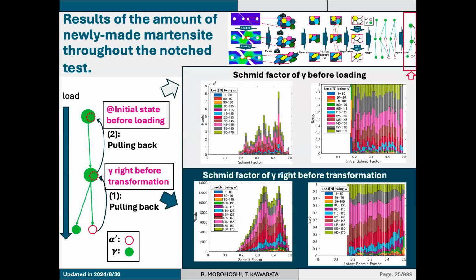So this is the slide about the Schmid factor. We believe that there are two ways to represent the Schmid factor. The first way is the Schmid factor of the austenite before loading. The second way is the Schmid factor of the austenite right before the transformation. So these are the results. The x-axis shows the Schmid factor and the y-axis shows the amount of newly made martensite. And the color bar shows when it is transformed into martensite. And at least I could say that the lower one is much more reliable because the neighboring bars don't change abruptly. And the trend is like that.